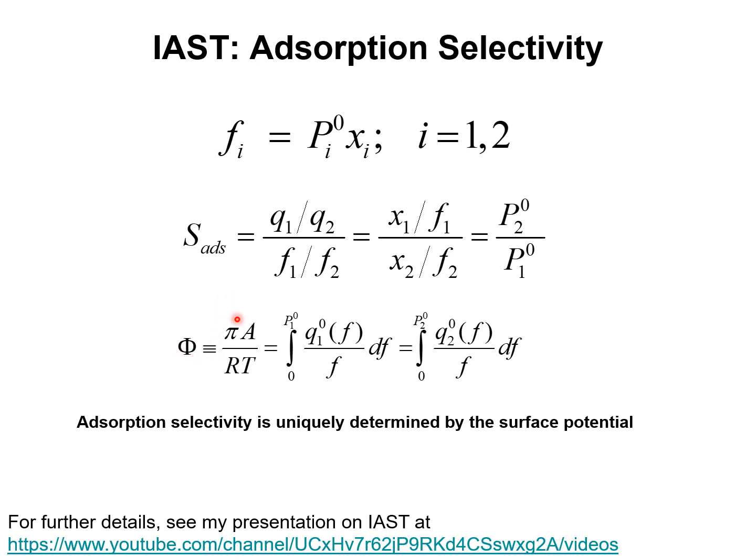And therefore, these expressions imply that the adsorption selectivity is uniquely determined by the surface potential irrespective of the compositions in the bulk fluid phase mixture. We shall test this conclusion using CBMC simulations of mixture adsorption equilibrium.